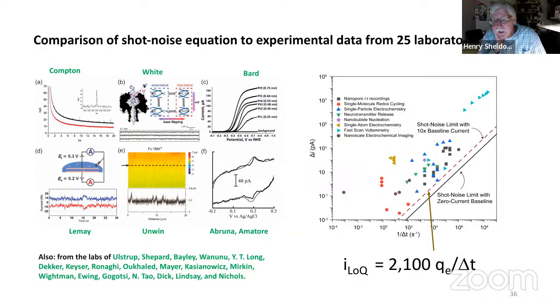It's not terribly surprising. In my lab, we have a lot more confidence in making electrodes that have a radius greater than 100 nanometers than we do making electrodes below 100 nanometers. The reproducibility and stability is much greater when you get above about 100 nanometers.